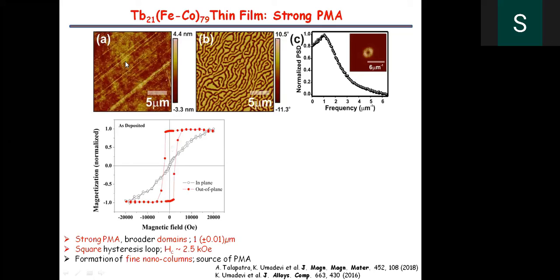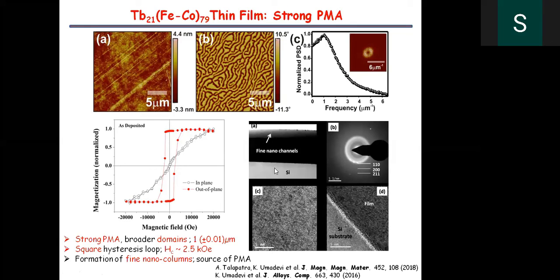The film grown with the composition 21 and 79 showed a very strong out-of-plane magnetic anisotropy. You see typical labyrinth kind of domain patterns, and the out-of-plane magnetization curves showed a high coercivity. The transmission electron microscopy study showed that the film-substrate interface is very sharp, we don't have any interdiffusion, and the films are found to be completely amorphous. We could see some nano channels growing, and these nano channels are responsible for producing the strong out-of-plane magnetic anisotropy.